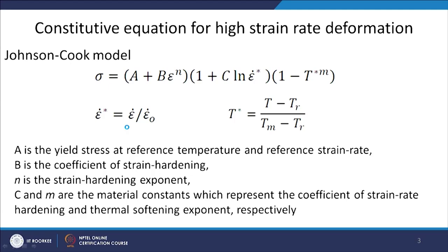So the sequence is a little bit different. We have done very slow strain rate, now we are doing relatively very high strain rate, 10 to the power 2 and more, and then we will be discussing the hot working, which is the main focus of our discussion. So again, phenomenological based constitutive equations, and the constitutive equation for high strain rate deformation. As I was telling you, in this case my strain rate will be more than 10 to the power 2. One of the most important or used models is what we call the Johnson-Cook model.